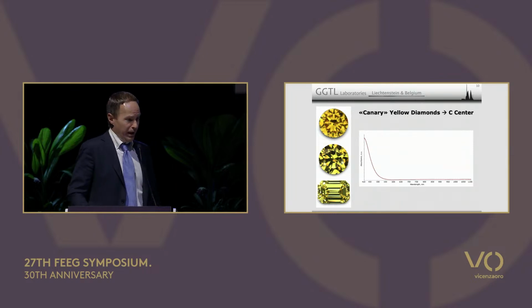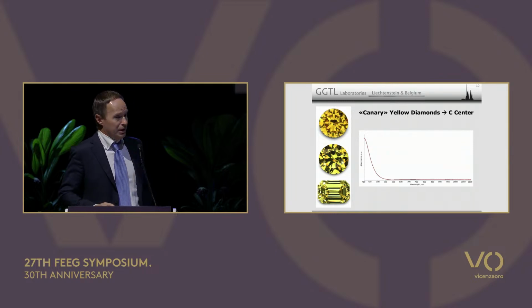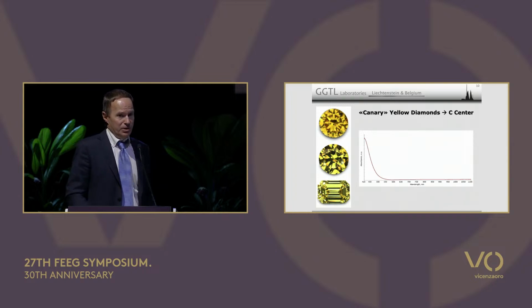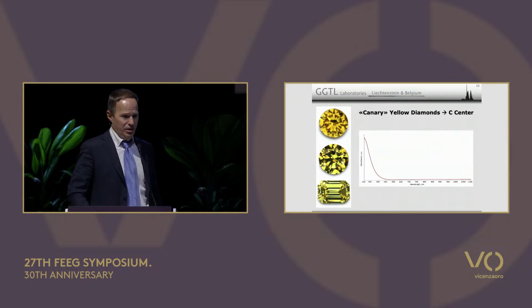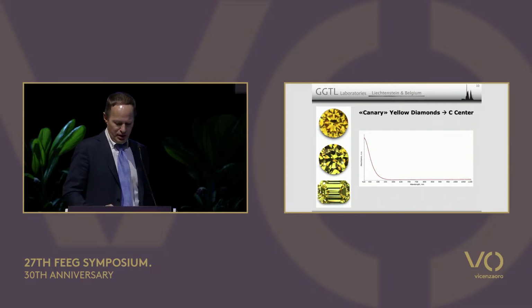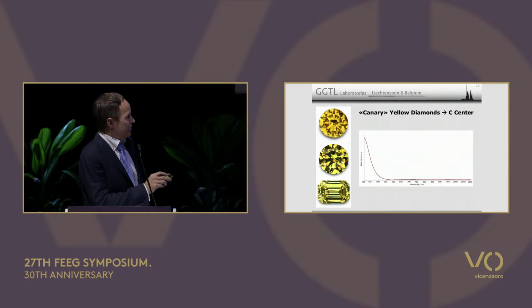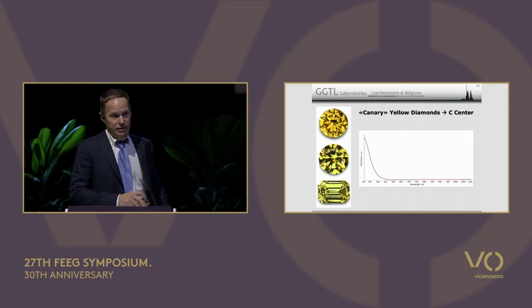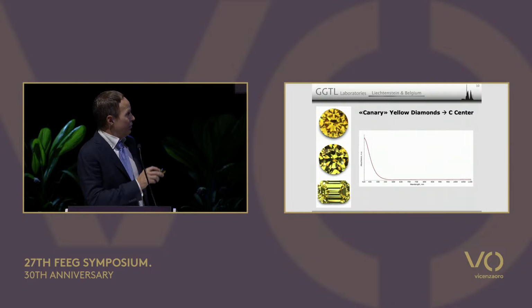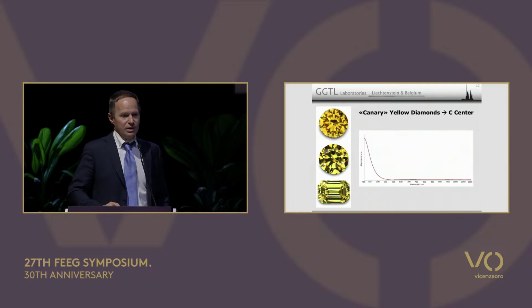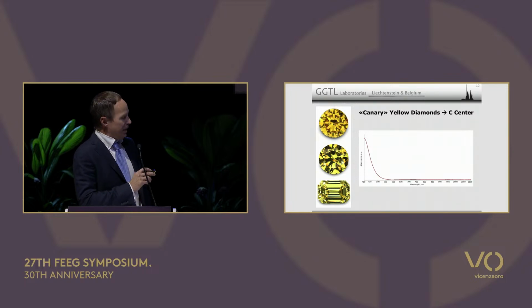Now, this is a much rarer type of yellow diamond. These are type 1b yellow diamonds, what we all know as canary yellow diamonds. They're colored by single nitrogen instead of aggregated nitrogen as in the N3 center. Here it's the C center that colors these diamonds. You can see the spectrum is very different. It's just a continuum, with no absorbance going on anywhere until about 560 nanometers. At 560 nanometers, your spectrum shoots off, and that's what causes this very intense and bright yellow color.